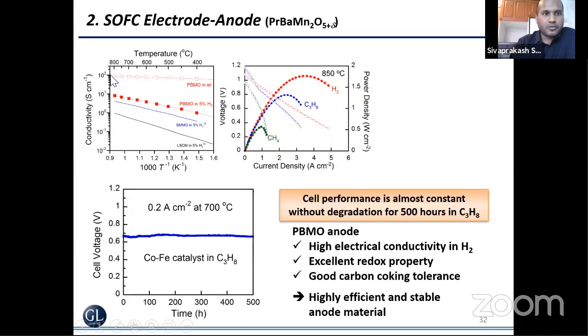As shown before, this shows high electrical conductivity, 10 Siemens per centimeter, and high performance at 850 degrees Celsius in hydrogen, with very stable performance in hydrocarbon containing fuels. In conclusion, the cell performance shows that without any degradation, high electrical conductivity was achieved, excellent redox properties achieved, and good carbon coking tolerance achieved from this data.